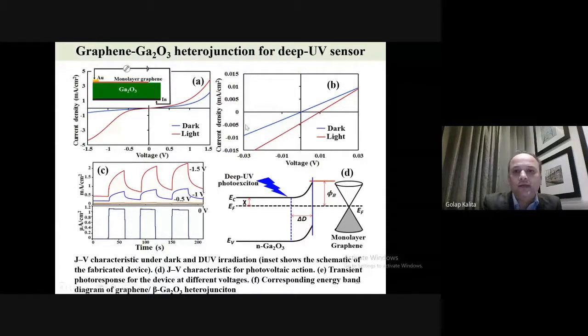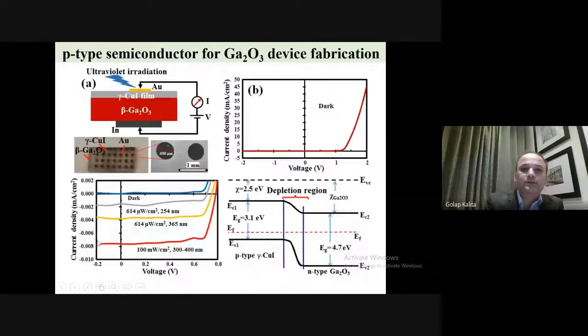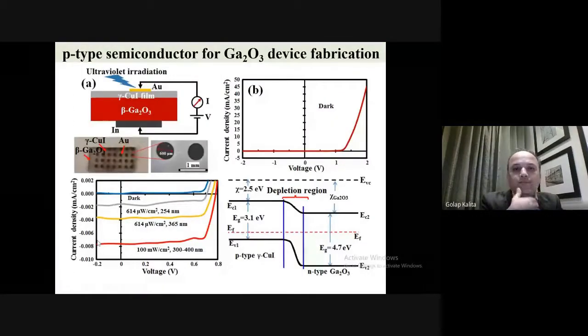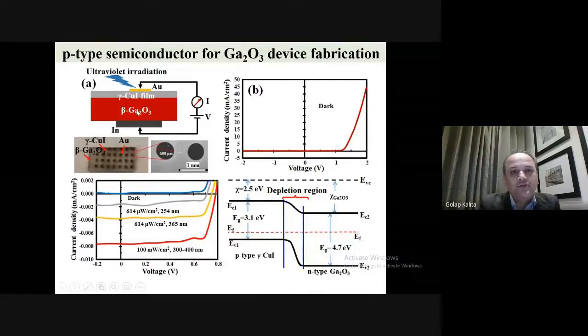So we can get photovoltaic action in this case also, in graphene gallium oxide, in the solar blind, deep UV region. We can use this also as a self-powered UV sensor. Okay, so it's a very interesting prospect. This is what we did with beta gallium oxide.